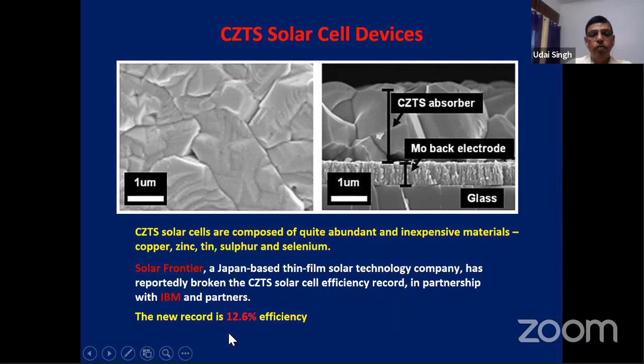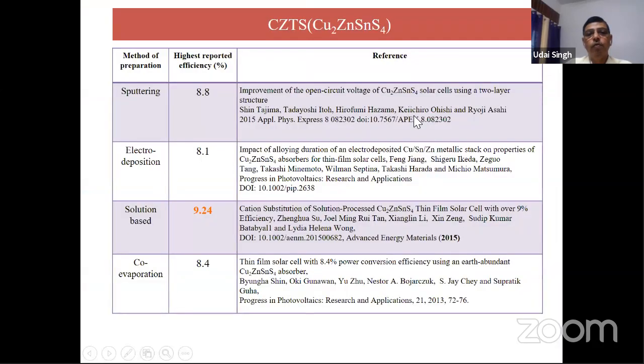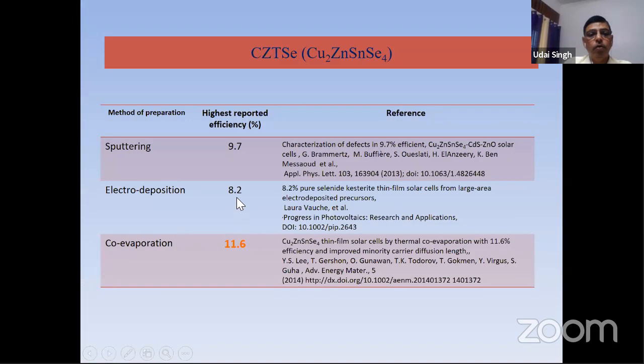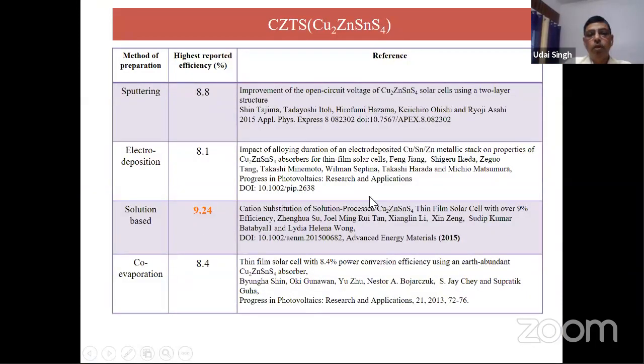If you see the efficiency, only 12.6% at the lab scale, and that was achieved in 2014. Now from 2014 to 2020, six years have passed, and nobody has crossed this limit. A lot of work is going on, but this efficiency has not been improved. So there are three variants. One is the copper zinc tin sulfide. People are using different methods: sputtering, electrodeposition, solution-based, co-evaporation. Using these methods, the highest efficiency achieved is around 9.24%, which is again way back in 2015.